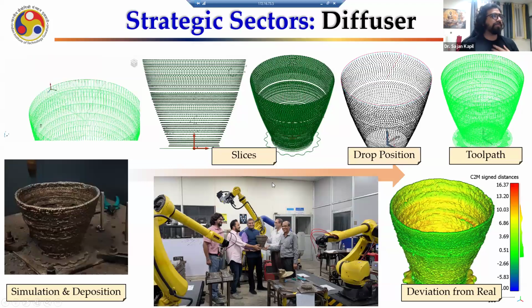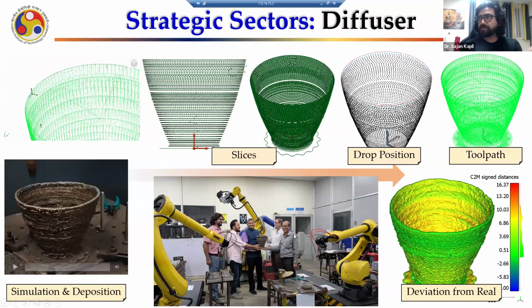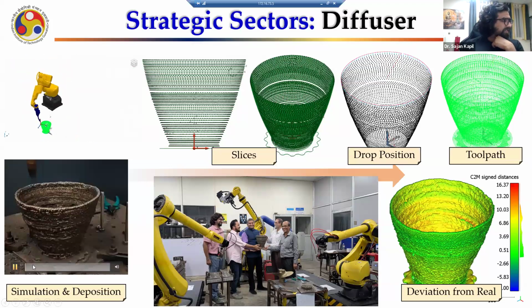The other one is the case we recently did for a space company. Again, in this case, you see we are depositing material, and it's Inconel. Inconel is very difficult to handle because its conductivity is very, very low. And if the conductivity is low, what happens? It sustains that heat, it does not conduct that heat, and that becomes a nightmare for giving a shape because it flows, again like honey, if you just continuously deposit. So we have to take a pause, but when to pause, how to pause, so that the desirable microstructure can be achieved. We did that, deposited and gave it to them. They are testing it right now.